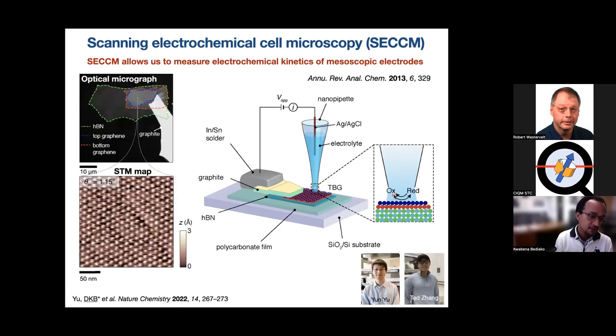And so we fabricate twisted bilayer graphene electrodes as per usual, but in this case, the surface of the twisted bilayer graphene is exposed. So for those of you who are in the know, you just flip the stack. If you know, you know. Anyway, the surface is then exposed, and we can use STM at room temperature to map out the Moiré superlattice and see that it is uniform over the sample and so on.